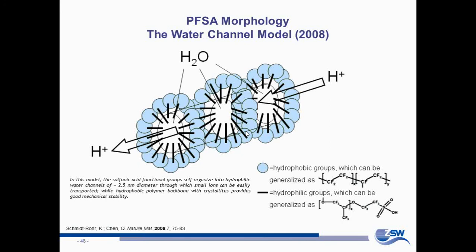So let's say from a practical point of view, if you don't do elaborate electrolyte science, you can look at these electrolytes as being something like nanosponges. You've got to fill them with water in order to make them highly conductive. It's pretty much as sulfuric acid. Pure sulfuric acid and pure water don't conduct ions very well, but mixtures of sulfuric acid and water are doing a lot better, and there is an optimum somewhere.